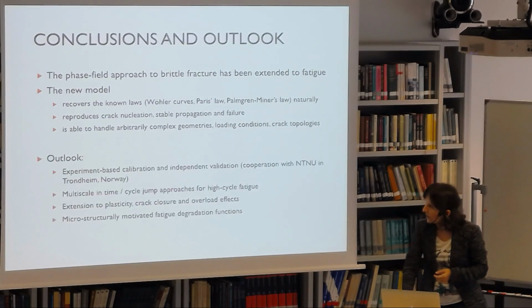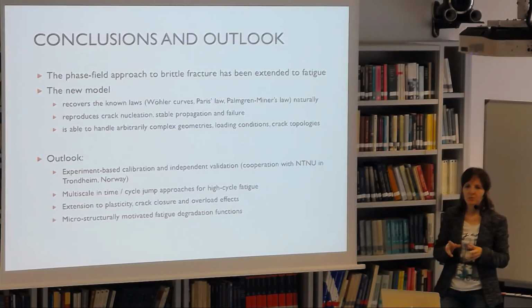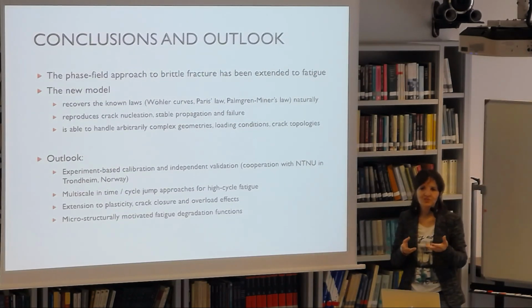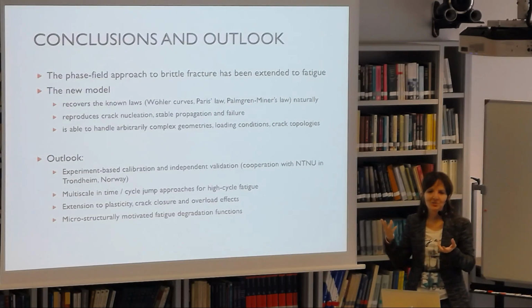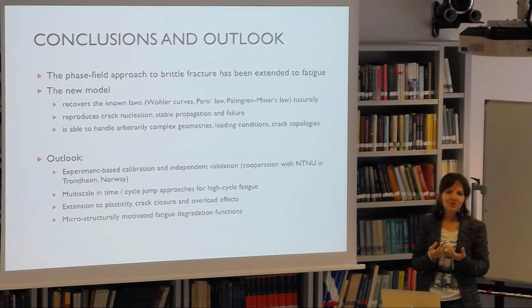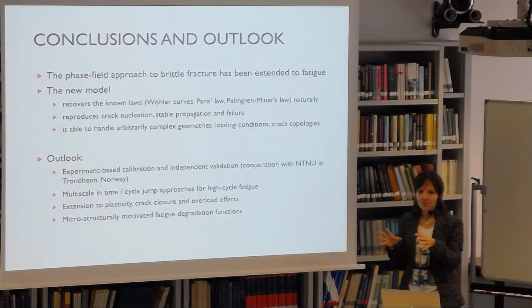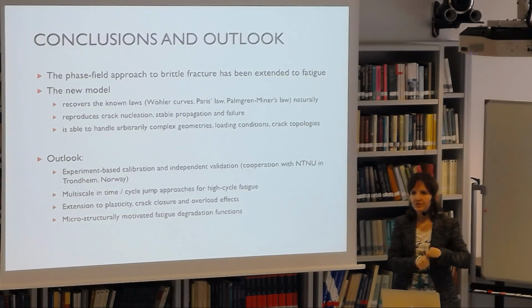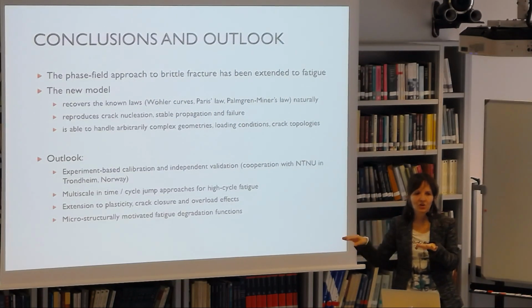crack topologies. And right now we are very focused on experimental validation, calibration first, because of course we need to calibrate. We don't need to calibrate as people typically do with experiments, but we need to calibrate our fatigue degradation function. So what we are trying to do now is to have sets of experiments where we can independently get, first of all, the standard material properties, so K1C, from which we can also compute GC, and then tensile strength, so that we can calibrate L based on the monotonic test, and then the fatigue degradation function should be calibrated to match, for instance, the Paris curve, and then we can independently validate with the SN curve, or vice versa.